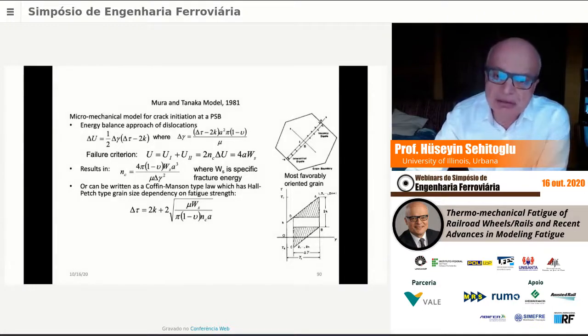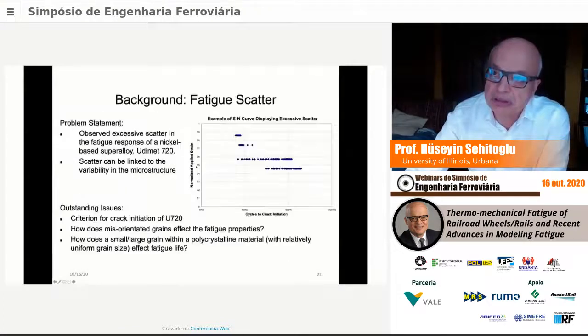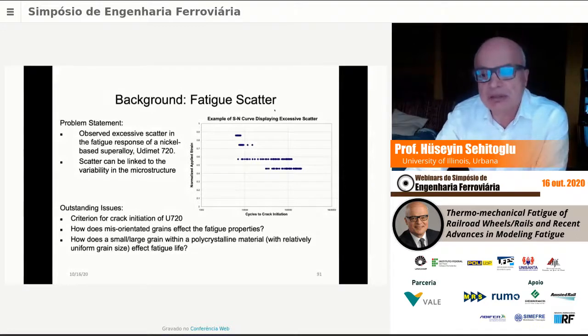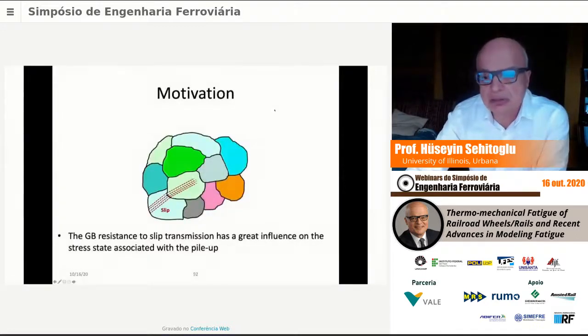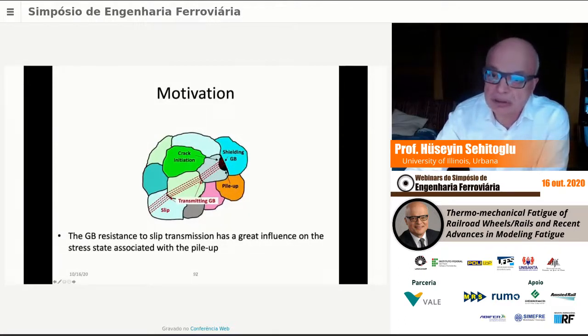The thing about these models is that they assume that the grain boundaries are pretty much rigid. It's based on the premise that there's significant dislocation pileup at this boundary and at this boundary, which is good as a first approximation. But we started looking at materials which show a lot of scatter in the fatigue lives. How could we develop models that account for this scatter and predict a life?